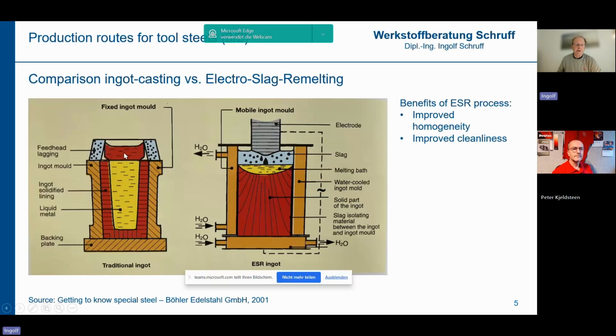We have a head section which is collecting impurities and will be cut off later. So this material can be used for many standard applications like forging, for example. But for applications with higher demands on toughness, mechanical properties, and so on, or if you have a very high alloy content, it is recommended to use a remelting technology. And in this case, the ESR or electro slag remelting technology. I mentioned that in this process we cast round ingots as the so-called electrode. That is here, this one.